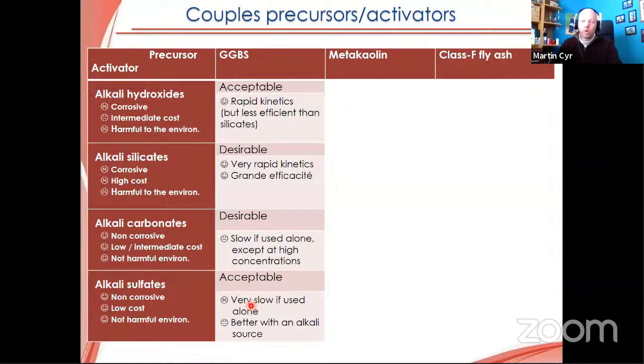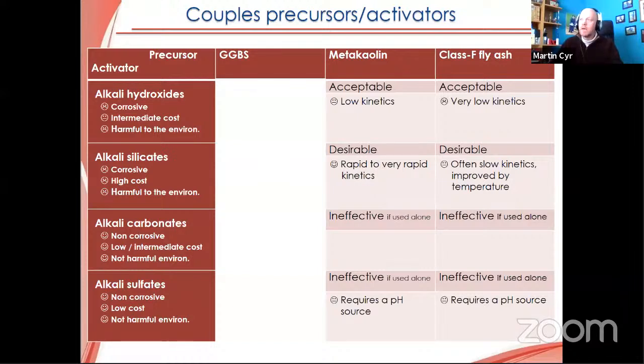Alkali sulfates are working quite well also. That's the base of supersulfated cement, which is maybe a little bit borderline regarding alkali activated materials, but it is still sometimes alkali activated. And of course, hydroxides are working well also, but often less efficient than silicate. What is probably more difficult is when we go around metakaolin and fly ash, because some of them are not working so well. The best one, best in class, is probably alkali silicates.